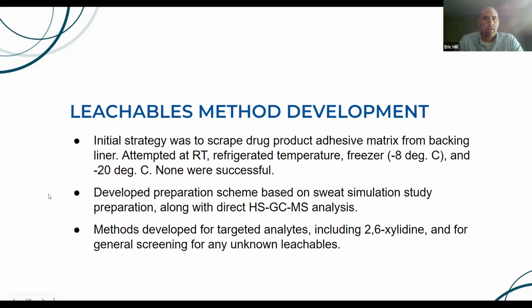Once we had that final list, then we went into leachables method development. Our initial strategy was to attempt to scrape that drug product adhesive matrix from the backing liner. Again, when we talk about leachables testing, we're always targeting to analyze the actual drug product itself. In this case, the drug product was in that adhesive. So we attempted to scrape that from the backing liner. And we attempted that under room temperature conditions. We refrigerated it. We tried freezing it, even down to -20.